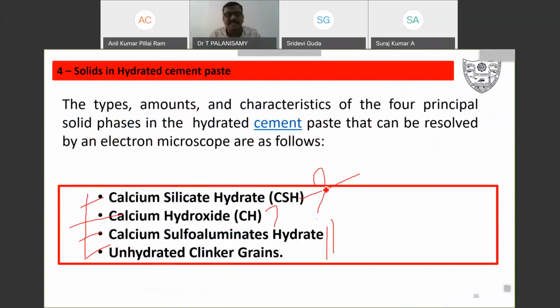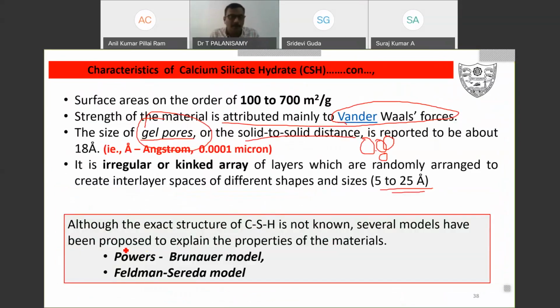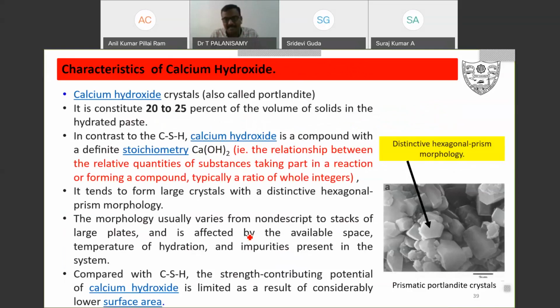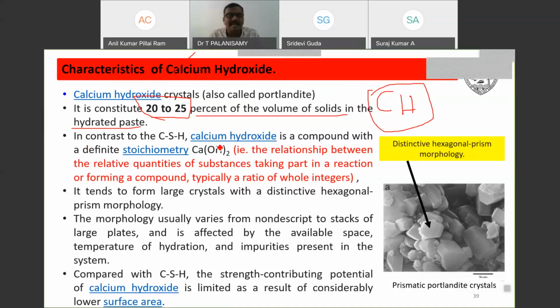Although the exact structure of CSH is not known, several models have been proposed to explain the properties of this material: the Powers-Brunauer model and Feldman-Sereda model. I will show this model so it is easily understood. The first solid is CSH. The second solid is calcium hydroxide, called CH. This contributes 20 to 25% of the volume of solids in the hydrated paste. So if researchers add any materials into the cement, or in fundamental cement development, you want to look at how much CSH content and how much CH, calcium hydroxide, we have.